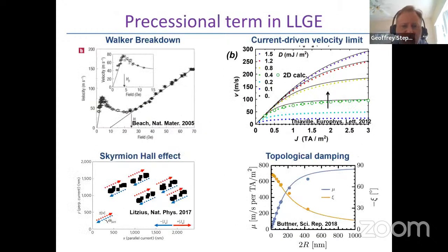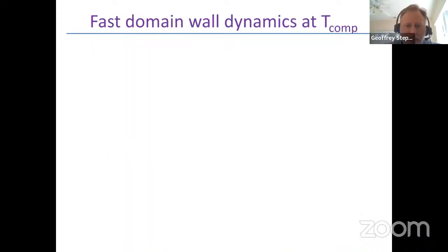And in fact, all of these effects for spin textures, Walker breakdown, skyrmion Hall effect, there are current-driven velocity limits for domain walls that are due to precessional motion, something I've not described here, but a form of topological damping for skyrmions that limits their velocity. All of these are related to the gyrotropic nature of dynamics in ferromagnetic materials. All of these undesirable processes vanish when a material is fully compensated. And so that's something that we and many others in the field are very interested in.